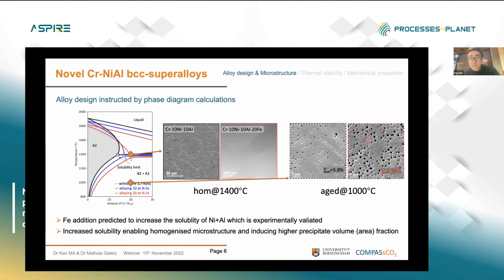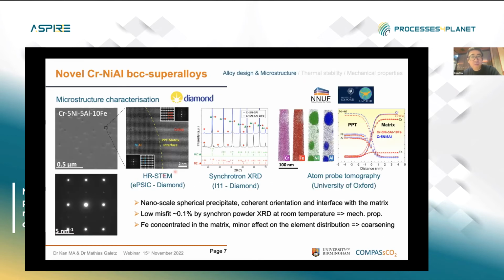And after obtaining this A2/B2 precipitate microstructure, we are interested in characterizing it. So what's the structure of the precipitate and what's their interface? Due to the limited time, I will just show some key results of a benchmark alloy: chromium, 5 nickel, 5 aluminum, 10 iron. As we can see from the micrograph, in most of the material we have nanoscale spherical precipitate with a cube-to-cube coherent orientation to the matrix, from this TEM diffraction pattern.